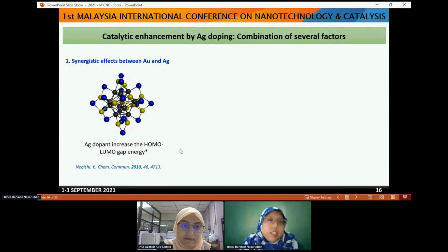So how did this catalytic enhancement occur through silver doping? Based on our analysis, we believe it is because of a combination of several factors. One of the factors is, of course, the synergistic effect between the gold and the silver. What we found based on our literature review is that the silver dopant actually increased the HOMO-LUMO gap energy.